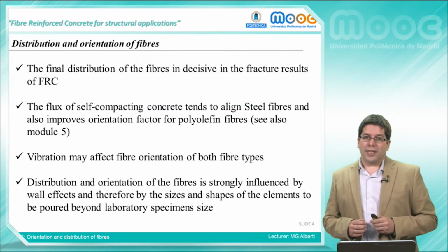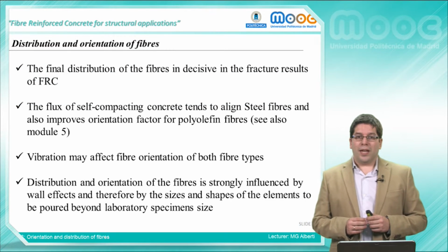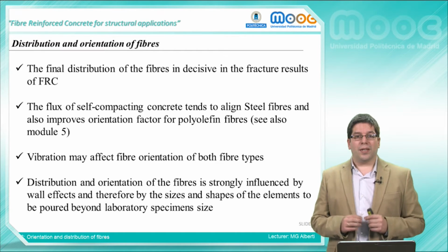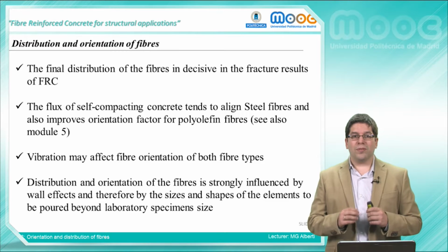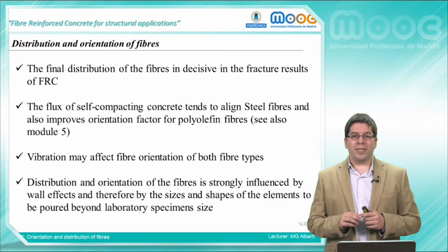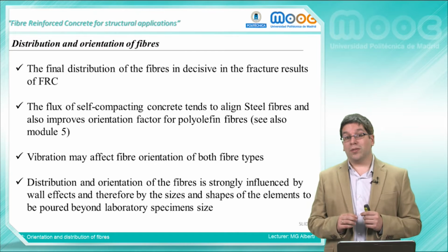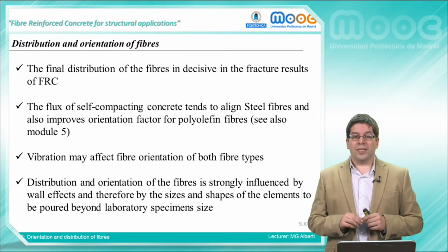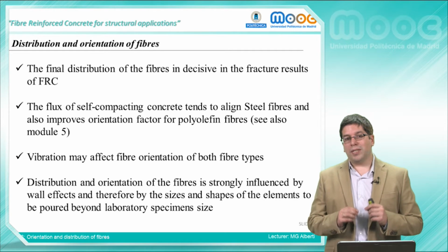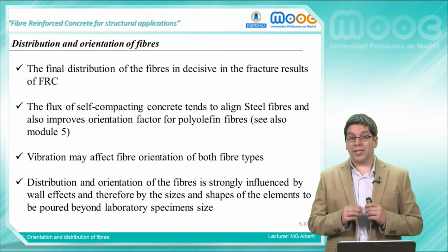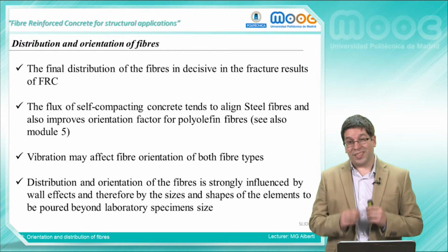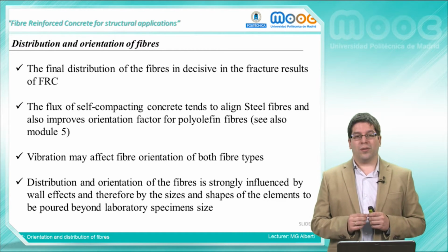It is well known that concrete is weak in tension, and a way of improving this characteristic is adding certain types and amounts of fibers. The latter, which are randomly positioned, might provide some additional residual strength to the concrete element when it bears tensile or flexural stresses. Since fibers are by definition randomly added to concrete during the mixing stage, the position and orientation of each isolated fiber depends on the pouring process, formwork geometry, and rheological properties of concrete.